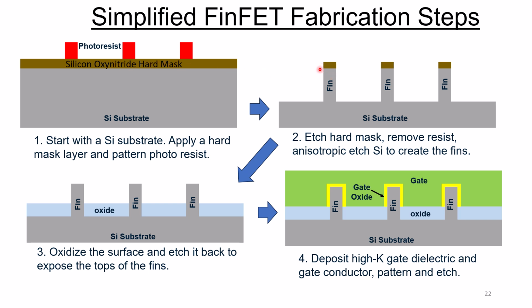And you etch the hard mask, and then you remove the photoresist, and you continue and etch the fins all the way down through the silicon substrate. So now you have the fins. Now you strip off the remaining hard mask, and you oxidize the surface, and you etch it back to just expose the tops of the fins. And lastly, now we go ahead and deposit a high K gate dielectric over the fins themselves, and then a gate conductor over top of that. And you etch and pattern everything, and you end up with the structure that we've shown before.